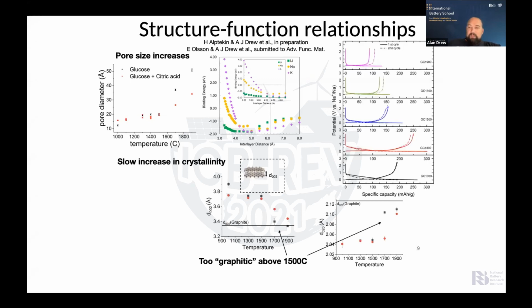Okay. And this is sort of borne out in the capacity measurements here. You can see that there's a peak capacity at 1300 degrees C, which is still up at close to 4. So the idea here is that we're increasing crystallinity, which we need in order to get sodium in and out, but there comes a limit where it can get stuck, so we get it in, but we can't get it out.